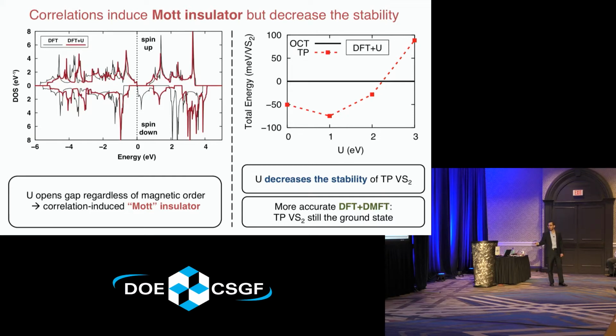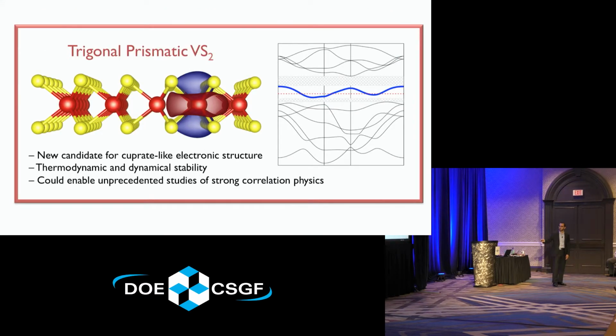However, using the more accurate DFT plus DMFT calculations, that is, solving that quantum impurity problem exactly, we find that trigonal prismatic VS2 remains the ground state. So this is pretty convincing evidence that not only would this be a one-band model, not only would it show signatures of strong electronic correlations, but actually there's a very good shot that this thing should be able to exist. So in this trigonal prismatic VS2, we've achieved this rare one-band electronic structure analogous to the cuprates.